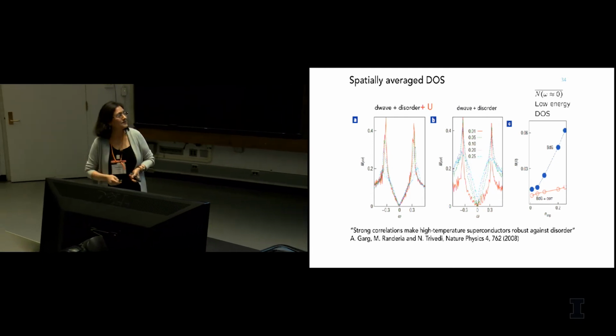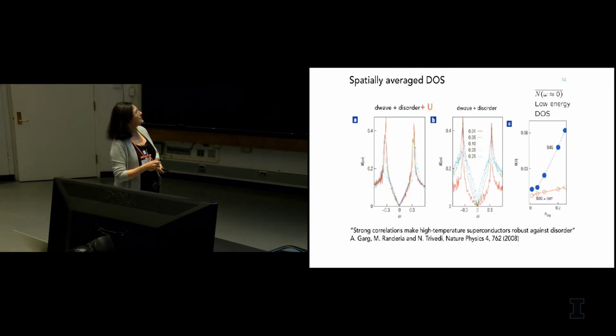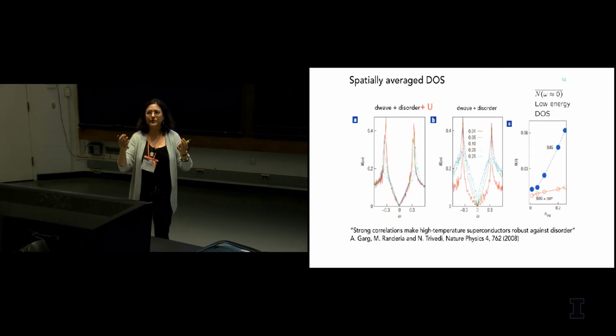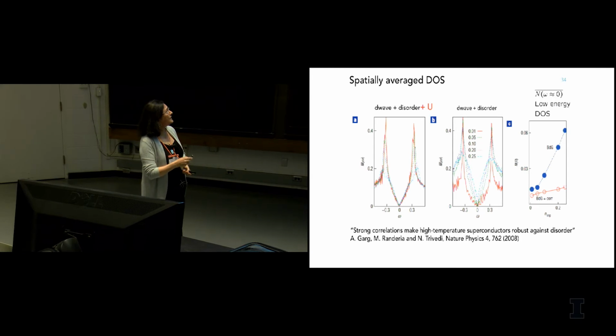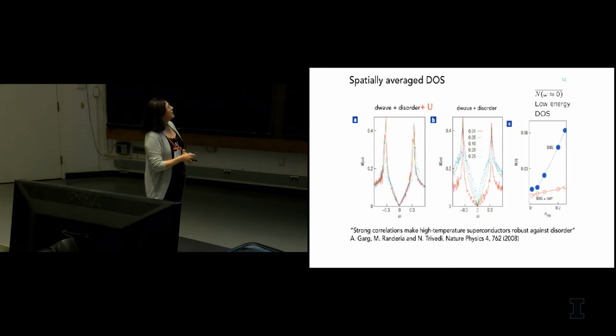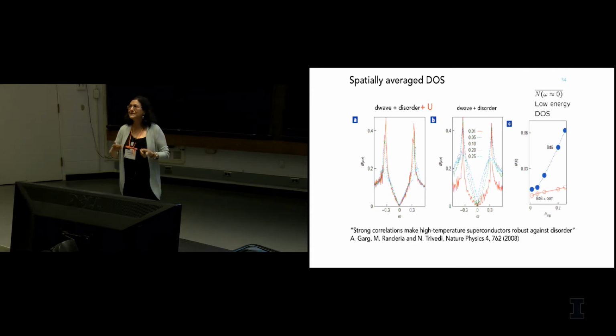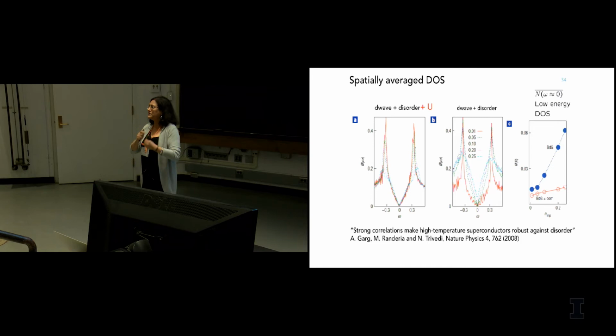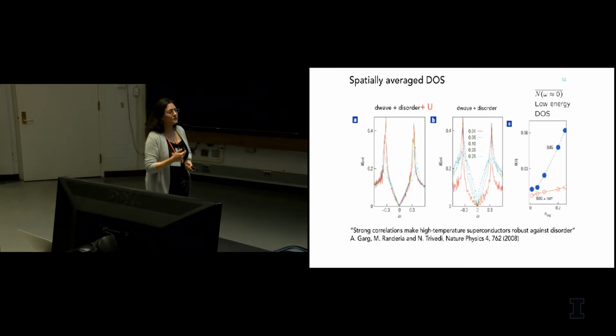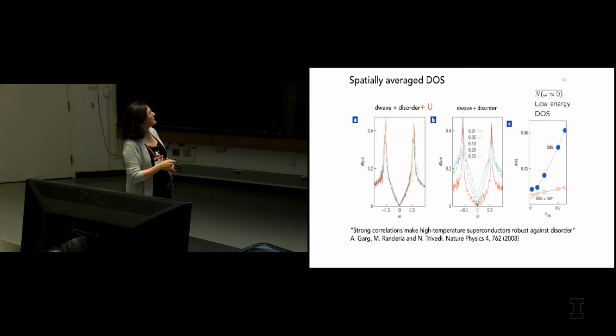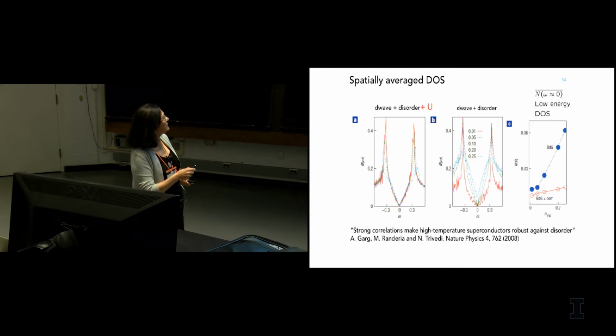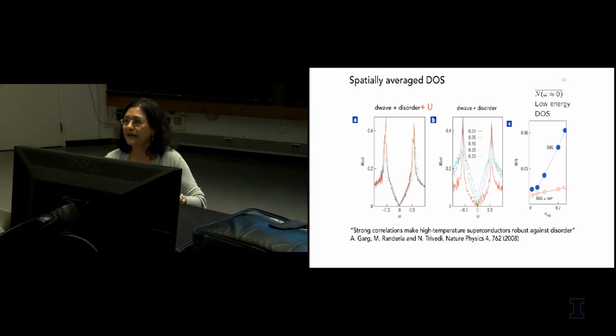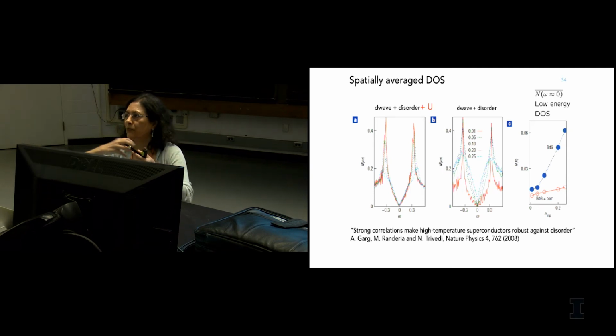So exactly why that is happening was what motivated me to go into this field, to understand why D-wave was so robust. And we have some explanation of that in which we were able to show that if you just put in D-wave weak coupling superconductivity with disorder, indeed then the low energy behavior is greatly affected. These are different amounts of doping, or disorder I should say. The low energy behavior is greatly affected. But if you put in the additional feature which cuprates have, ultimately they are D-wave-like because there are strong interactions. And when you put in the additional feature of the strong U, then the low energy density of states is indeed very robust against almost 25% disorder. And this comes down again to the fact that the scattering is mostly within one of the lobes of the D-wave order parameter and not between them.